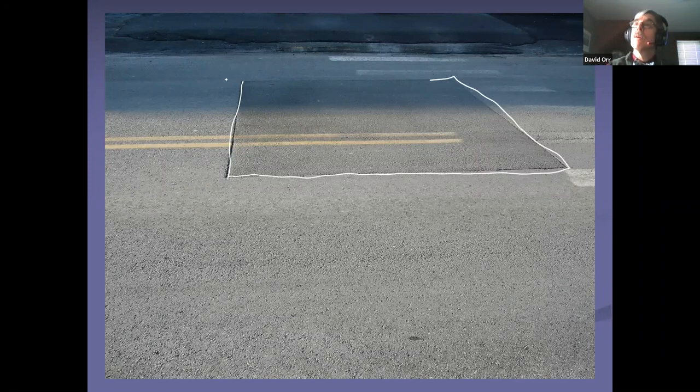Okay. Now, this person asked a good question with regards to alligator cracking and base failure. Has the asphalt base failed or the sub-base material failed? Most of the time we see alligator cracking, that's usually a drainage problem. There's a water issue underneath. It's usually lower down. Not always. Some old pavements will look like alligator cracking, but it's usually deep down. It's usually the base or sub-base or the native material, even the subgrade itself. Yeah, Gary says sub-base, and Gary's right.